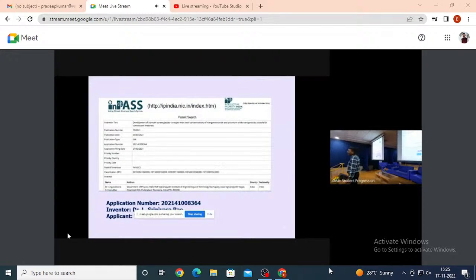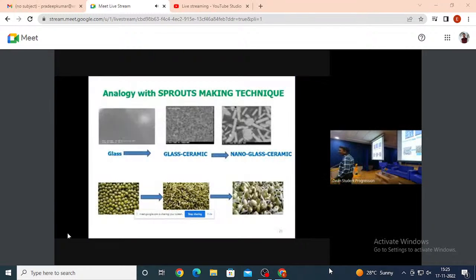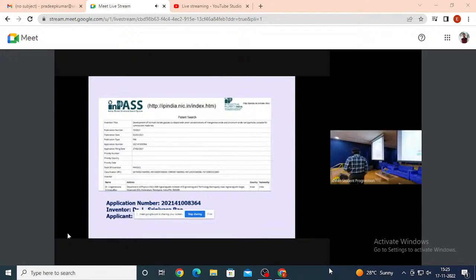And I filed a patent. The previous slide may be very simple for you, but I copied this concept and prepared bismuth borate manganese glasses doped with zirconium nanoparticles. The manganese and zirconium act as the seeds in my glass. When I heat them, they grow like a plant inside the glass network, and I get the nano rods. I will show that. The nano rods like this. These are the zirconium and manganese particles. We have published a patent, and we got the response very soon that it will be granted. This is the patent number.